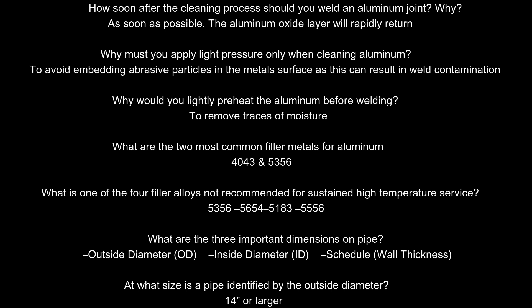Why would you lightly preheat aluminum before welding? To remove traces of moisture. What are the two most common filler metals for aluminum? 4043 and 5356. What is one of the four filler alloys not recommended for sustained high-temperature service? 5356, 5654, 5183, 5556.